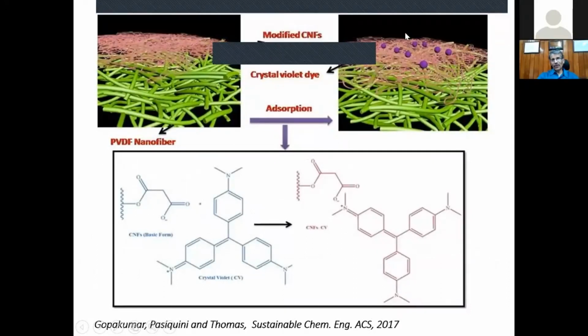But dear friends, we can make fantastic filters by using nanocellulose. And if you look at the chemistry, this is the chemically modified nanocellulose. This is the crystal violet dye. It can form electrostatic interaction, the dye and the nanocellulose. You can see all these crystal violet molecules have been retained at the top of the filter surface.